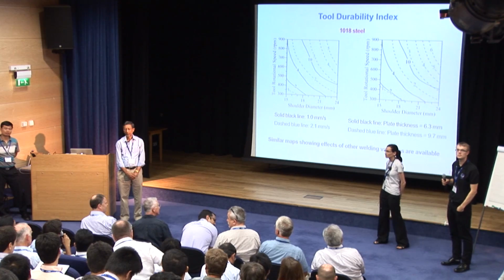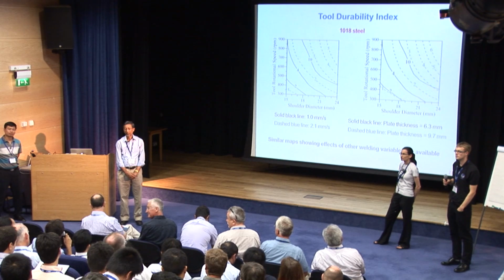That was a nice talk, but I have a question on the mechanism of this friction stir welding. People say there are two types of diffusion mechanism. First is thermal diffusion, other is ballistic diffusion. So in your view, which mechanism is most important for friction stir welding? You know, the most important diffusion is thermal diffusion, because without heat, there is no welding, even for solid state welding. That I understand, but in your work you have said that the tool speed has a very strong influence on the microstructure development. So from there it came into my mind that if the tool speed is so important, then there must be some influence of ballistic diffusion in that case.